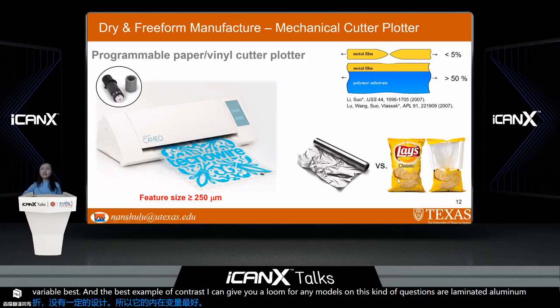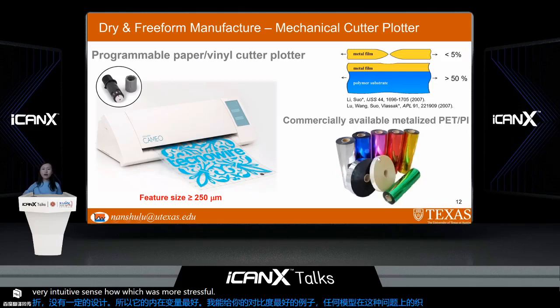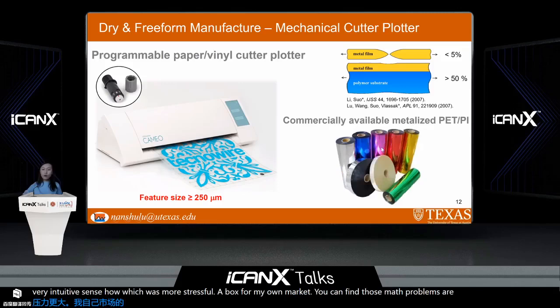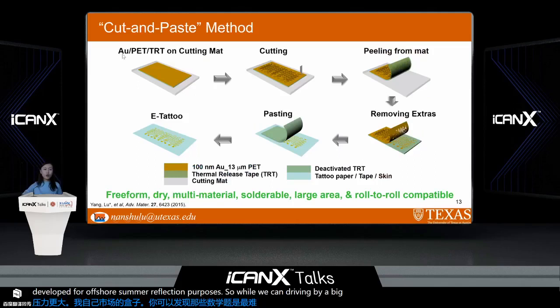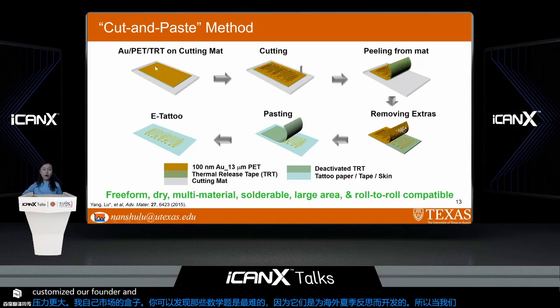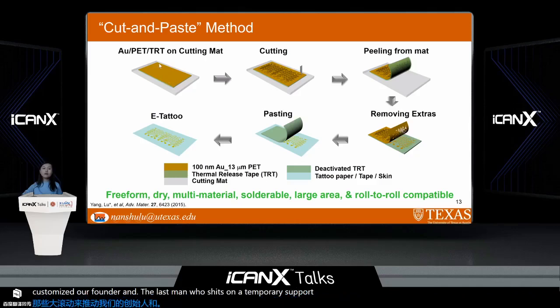And so fortunately on the market, you can find those metallized polymers as big rolls. They are developed for RF shielding or thermal reflection purposes. So we can directly buy those big rolls of gold on PET or copper on Kapton, or you can customize from the vendor. And you laminate this metallized polymer sheet on a temporary support, such as a thermal release tape. And you put it into the cutter plotter, either mechanical or laser, and you can form those cutting seams.